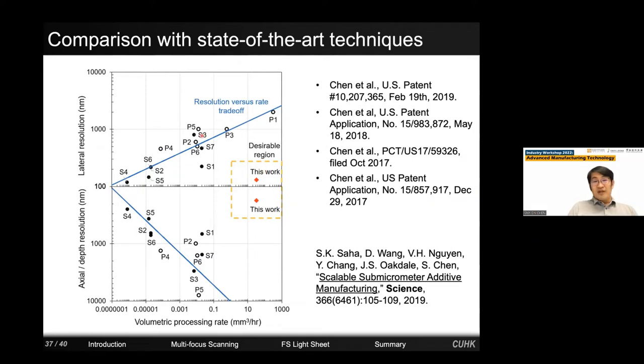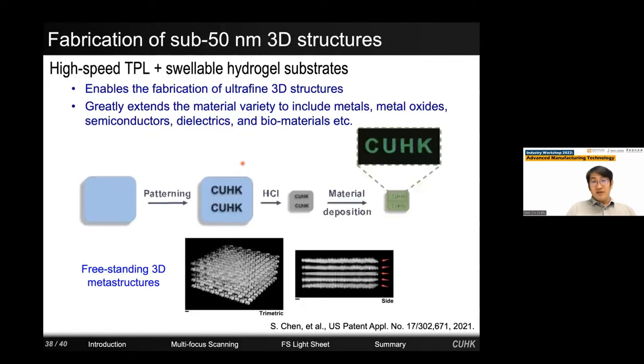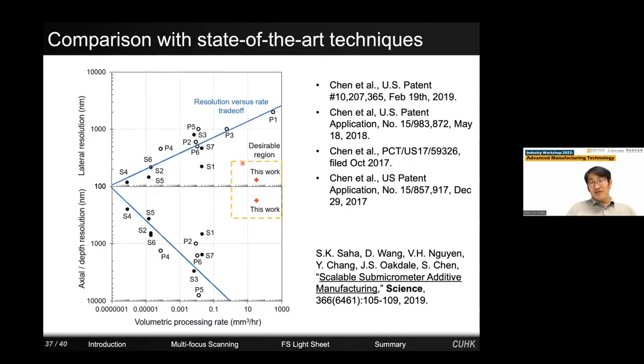If you compare this work with all other works, you can see most other works are playing with the trade-off between speed and resolution: high resolution, low speed; high throughput, low resolution. But we fundamentally address the issue and simultaneously achieve high speed, high resolution, and low cost through this work. Okay, but there is a limit on the resolution we can achieve, roughly 100 nanometers. On the other hand, many metastructures, especially in visible light applications predicted by scientists, require features below 50 nanometers. And that's an area that we are working on right now.